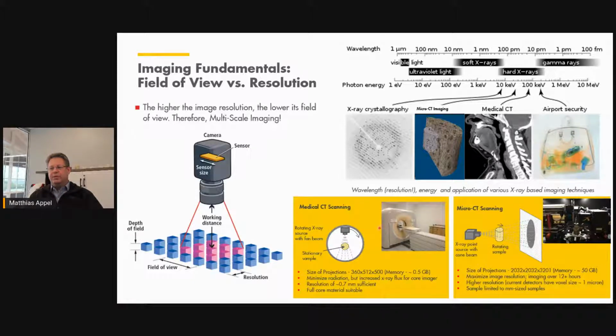Here we have, again, I remind, simply a source and detector arrangement rotating around the sample. For the micro CT imaging, we have a sample rotating in front of the detector and an X-ray source. We have differences in the projections and therefore the resolution and of course the image sizes. But the price that we are paying by working with this very high resolution is that we are limited to millimeter sized samples, whereas a medical CT scanner can image an entire core, an entire body. As a matter of fact, somebody could go into the CT scanner and hold the core with their hands to keep it steady. Don't do that, because these core CT scanners have had their X-ray intensity increased by about a factor of 10, so not a good idea to do that.